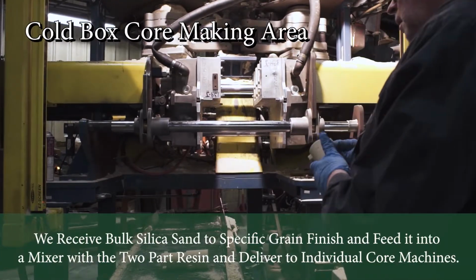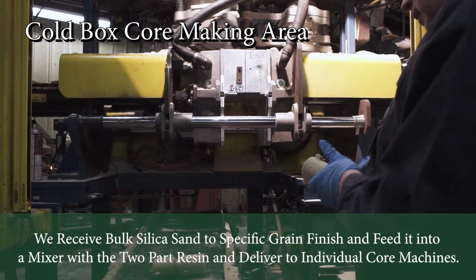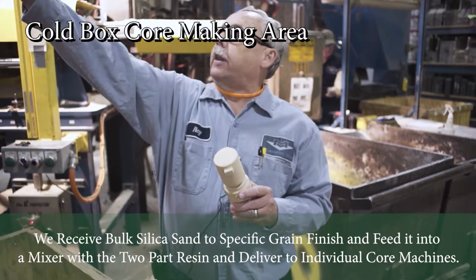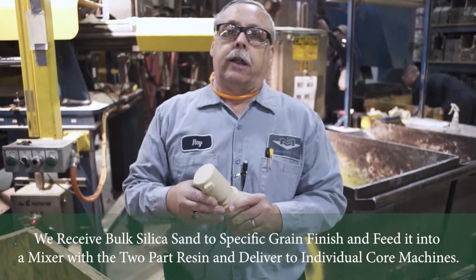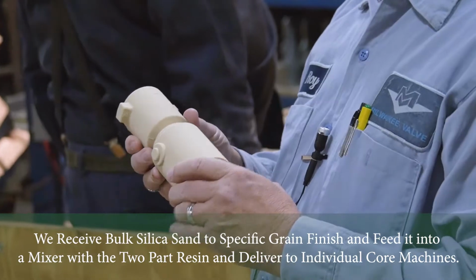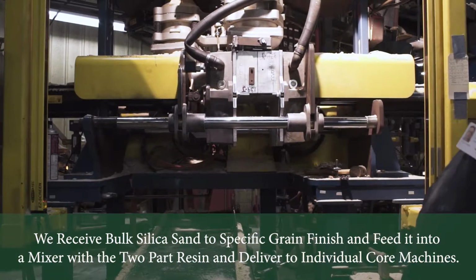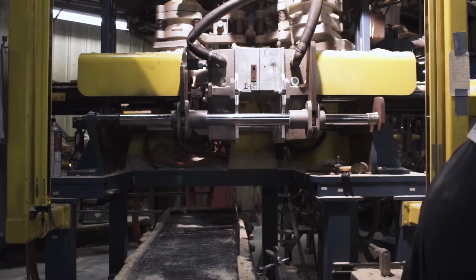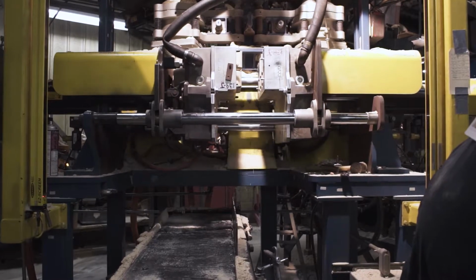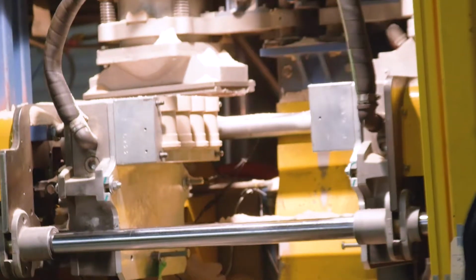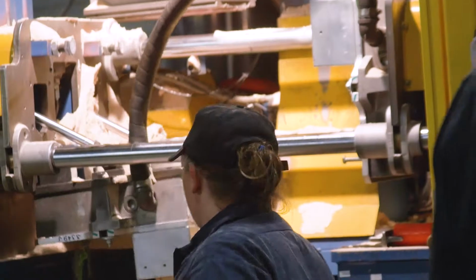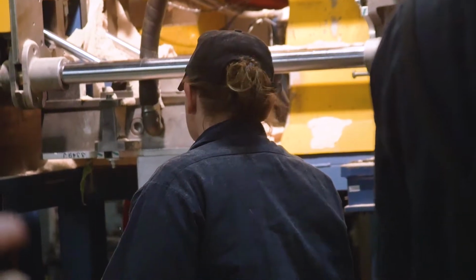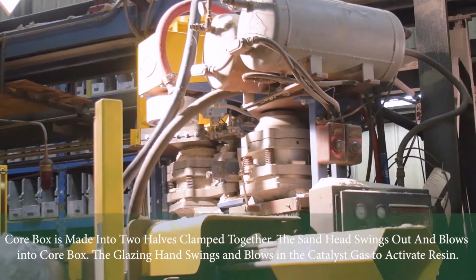This would be an isocure core that we have. We again buy bulk sand that's delivered to the machine. We automatically feed it to a mixer. That mixer will put the amount of resin in and mix it on a continuous basis. They can call for different resin content at each machine, and it'll give that resin content and mix it with two resin, and then we blow it into a box.